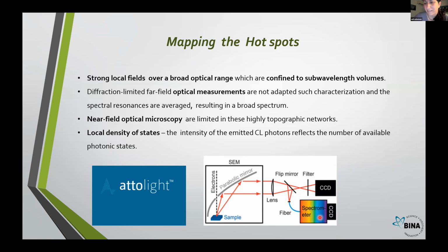In the end, we want to map the hotspots to design this plasmonic structure and to understand what is going on, what the model of hybridization is, and so on. But we have a problem, because we have a strong local field over a broad optical range from the UV to the IR, and these strong fields are confined to sub-wavelength volumes. So for sure, we cannot use optical measurements, which are diffraction limited. They are not suited for such characterization. And once we measure these structures, especially the metallic network, by just linear optical measurement, it all averages out and results in a broad spectrum, which doesn't really reflect the optical properties of the plasmonic structure.